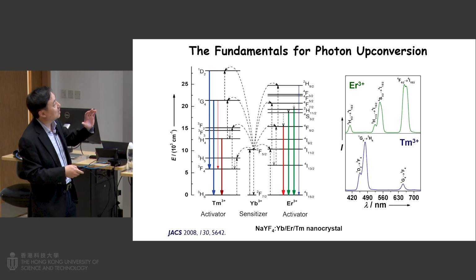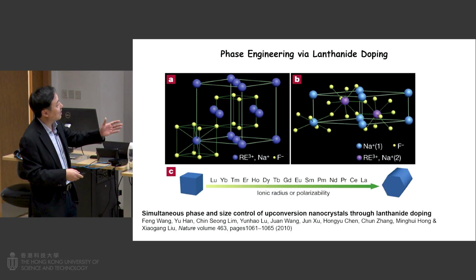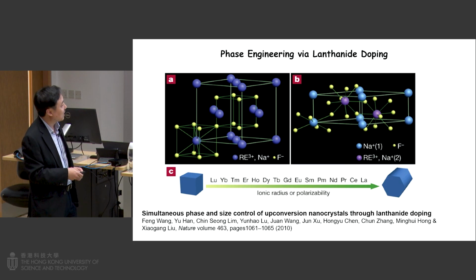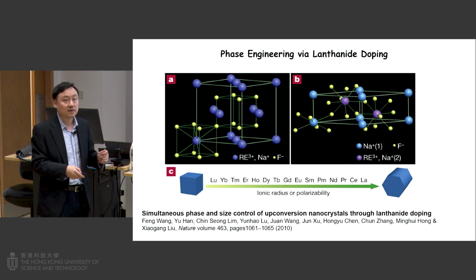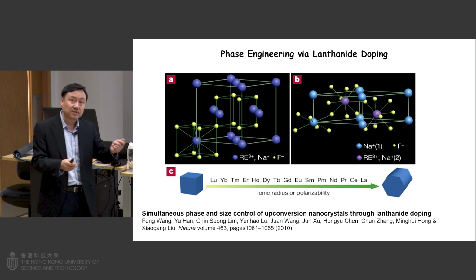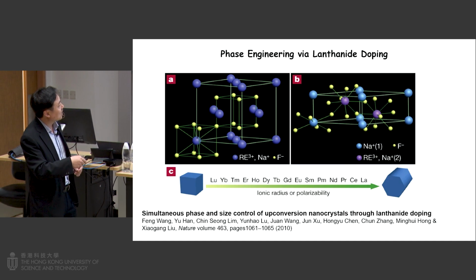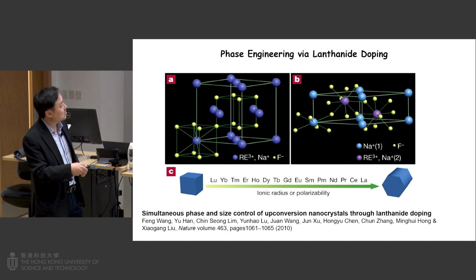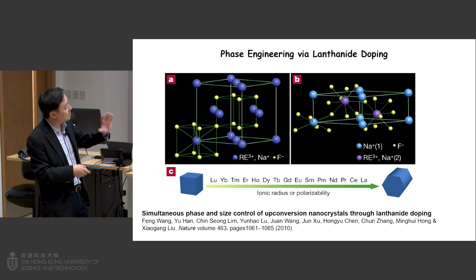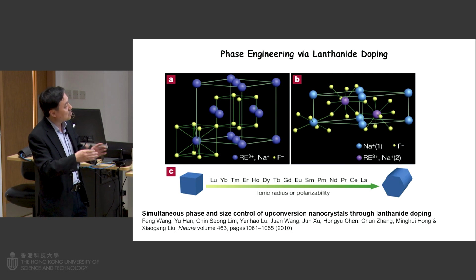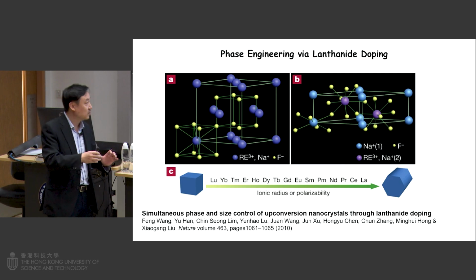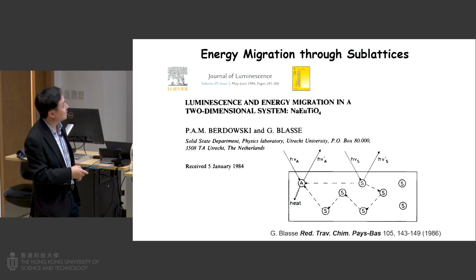You can also tune the colors by varying the dopant concentration. I want to highlight this. This is quite important work in the field. We published it almost 15 years ago. We realized that using lanthanide dopants, we can control the crystal phase. This is a quite interesting study because you add some lanthanide ions into the crystal structure, and you can see we control the cubic phase to hexagonal phase by introducing the lanthanide ions. It is still a very interesting study. Because we add lanthanide ions, we change the polarizability of the crystal field, and then we can achieve this phase tuning.